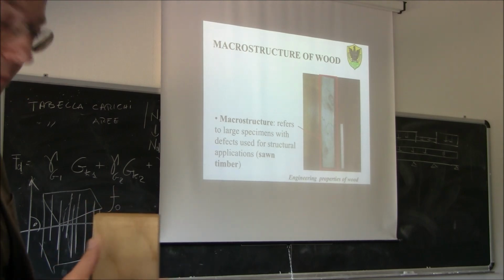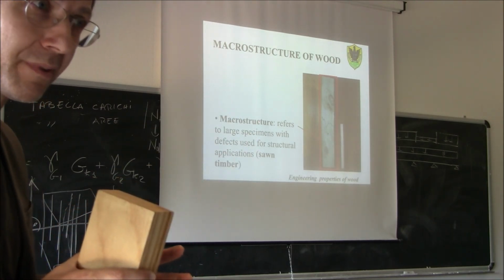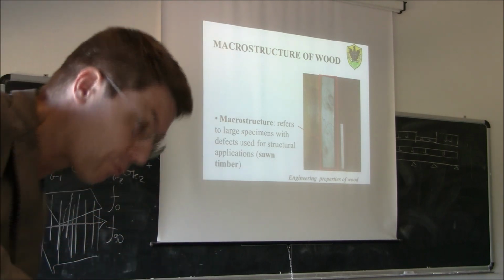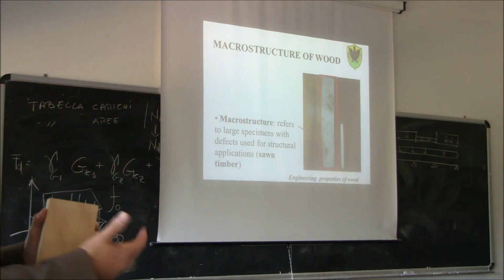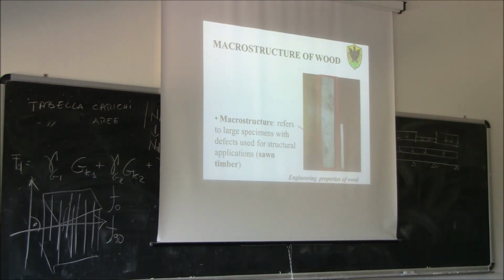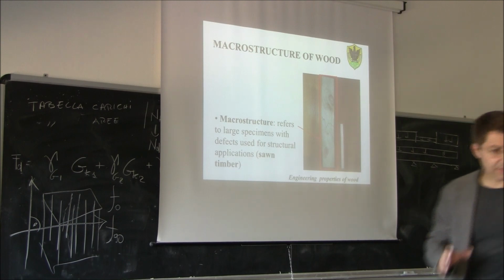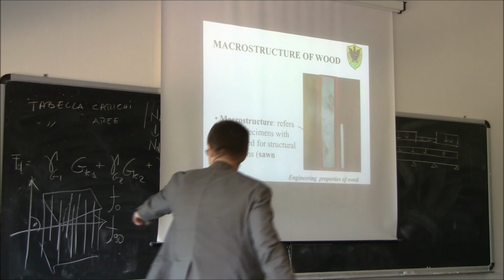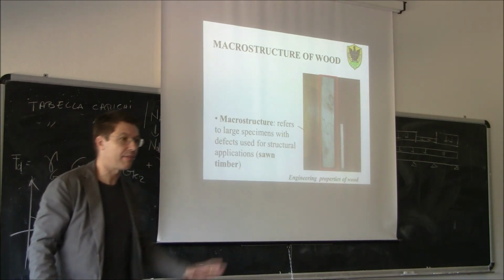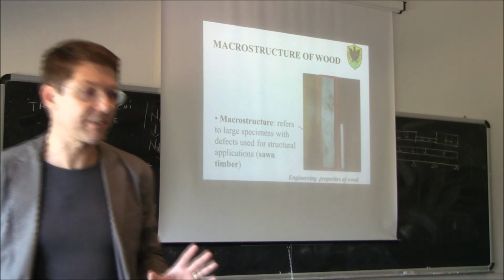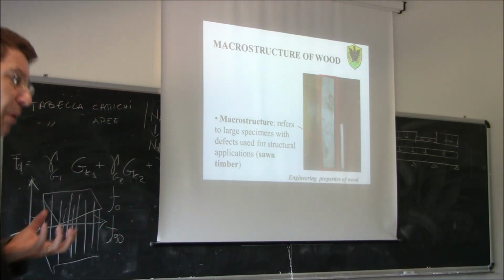Because they are slender, but they are in a continuum. They're not only separate. I'm not going to buckle a straw. The straws are surrounded by a matrix, so there is a continuum of solid. It's not a single straw. So why is it going to buckle if I have a continuum? Because it is a low density of the matrix. Yes, because the fibers are basically surrounded by a very weak and less resistive matrix. So the matrix is the weak point.